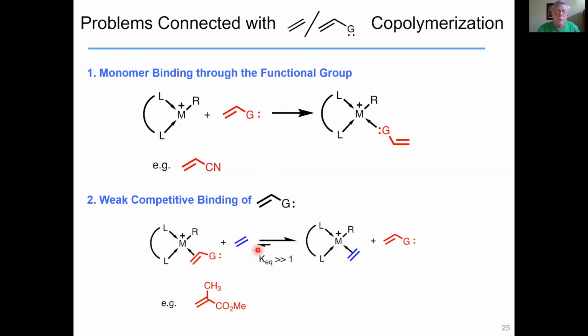There's also an issue of weak competitive binding. The metal center is electrophilic. If you have a bulky, fairly electrophilic olefin like methyl methacrylate, you simply don't compete with ethylene. This equilibrium lies far over to the side of the ethylene complex, and so you never generate enough of the olefinic complex of the polar monomer to propagate or to incorporate very much of that into your polymer.